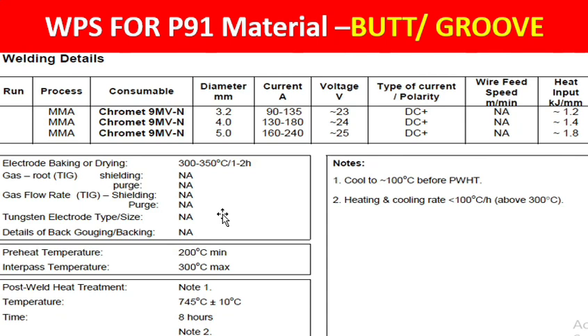So only the MMA welding, that's why electrode baking is required. Preheat temperature is 200 degrees centigrade minimum. Interpass temperature is 300 degrees centigrade maximum.